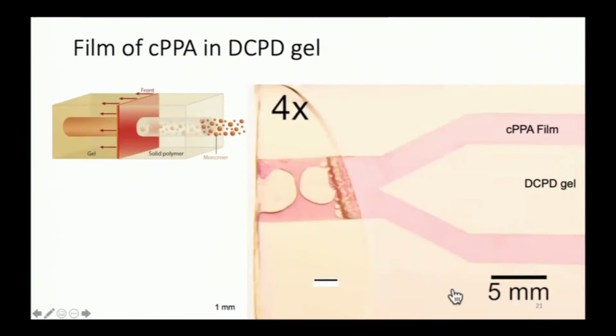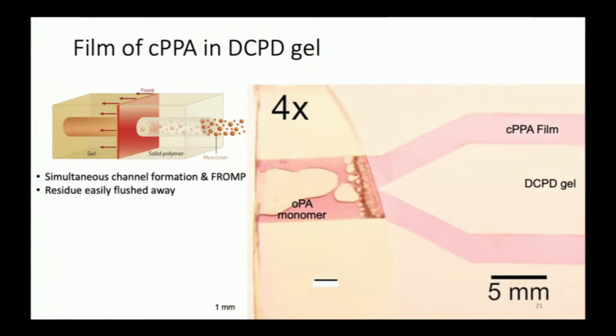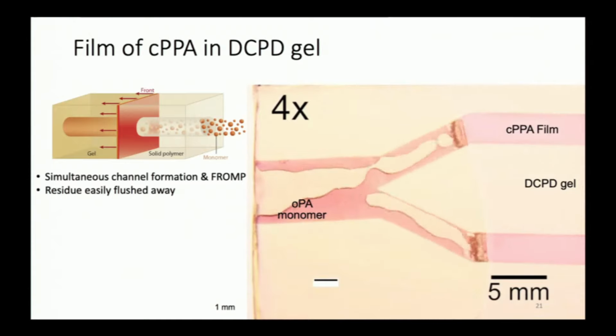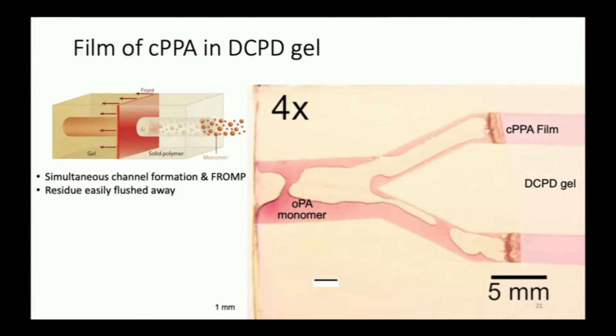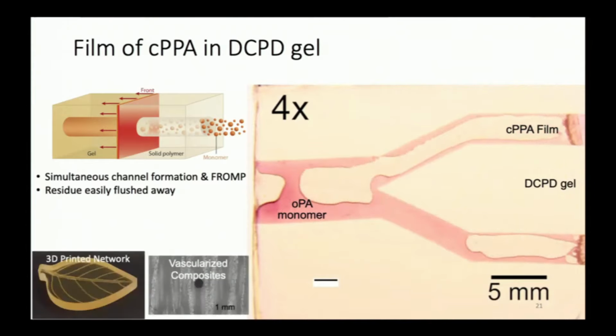And so this video is an example. You can see the front propagating through. This is a cyclic phthalaldehyde, polyphthalaldehyde film, and as you watch, sped up 4 times, the liquid monomer is trailing behind, leaving a void space. And so now we can simultaneously cure the material with the frontal polymerization and simultaneously depolymerize the materials that will leave behind our vascular structure. We've created things like this leaf object just for fun, but we've also been able to move this into vascularized composites.